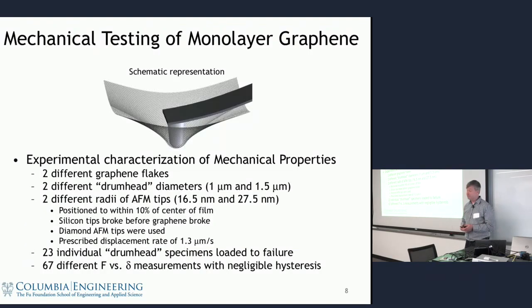So here are some of the details of the experiments we did. We did this for a few different graphene flakes, different drumhead diameters. We used different AFM tips, put them right in the center of the film. One thing we noticed, and the reason this experiment took about a year to complete and start writing up, was that we spent a lot of time with regular silicon AFM tips. And if you just kind of don't think about it too much, you think, I've got a material that's 1 atom thick. I've got a somewhat macroscopic tip that's, say, 20 nanometers radius. I should be able to just punch through that no problem, even though the graphene is probably a little stronger than silicon. There's so much more silicon there.